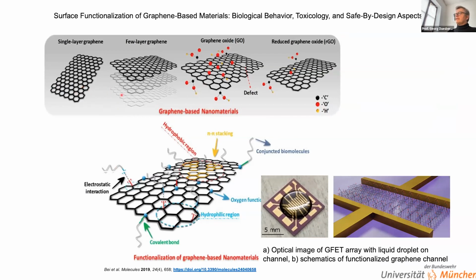You have different starting materials: single layer, few layer graphene, graphene oxide, or reduced graphene oxide. Also exfoliated graphene and so forth. And then you can think of a lot of different chemical reactions, starting from covalent bonds, going to pi stacking, or just adhering particles to it. But at the end of the day, you have to watch out that you always modify this material already during this step. So I pursued very much the idea of a non-covalent bonding of molecules, leaving the graphene in a pristine state and just giving the functionalities on top.